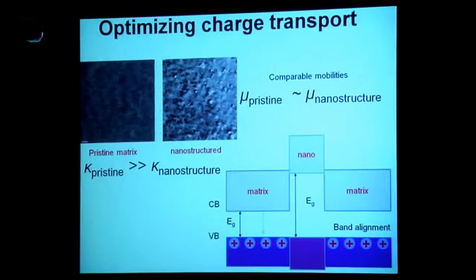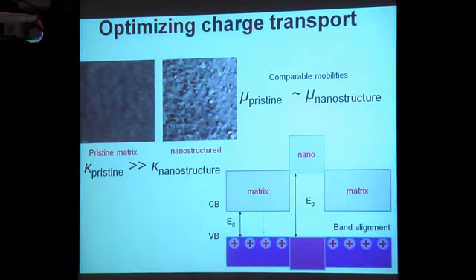So why doesn't the mobility go down? We have the thermal conductivity of the nanostructure is much less than that of the pristine material, so that's good. We're scattering the phonons. But the mobilities are the same between the two. So here's how we explain that.